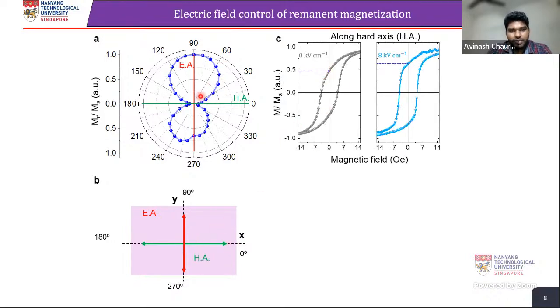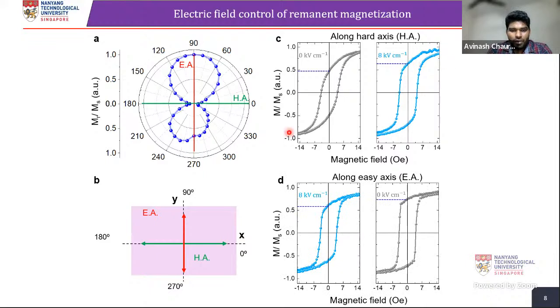So at 0, the remanence was lower here, so we see the hard hysteresis loop in the system. But when we apply the electric field, we can see the increase in the remanent magnetization, which is directly correlated with the increase in the terahertz amplitude. But when we align the sample in the easy axis direction and apply the electric field, our remanence decreases in comparison to 0 kilovolt per centimeter, which is the opposite behavior to what we got by rotating the sample in the previous slide. So from here, we can say that it is the easy axis rotation mechanism through which we are able to control the terahertz spin current by applying the electric field.